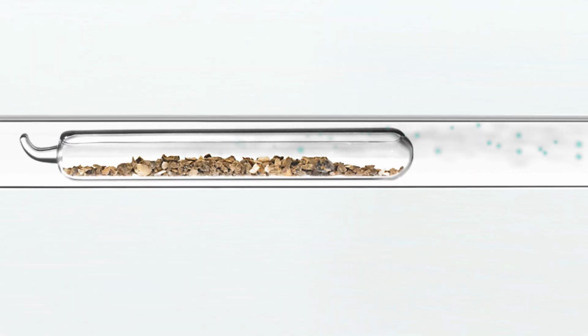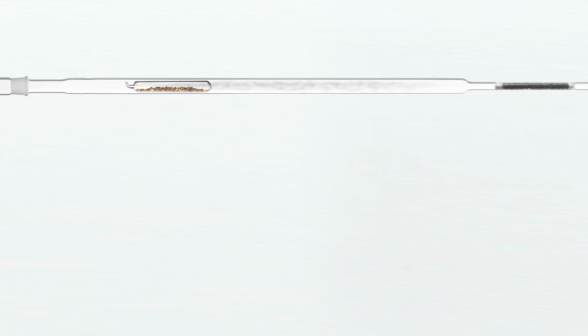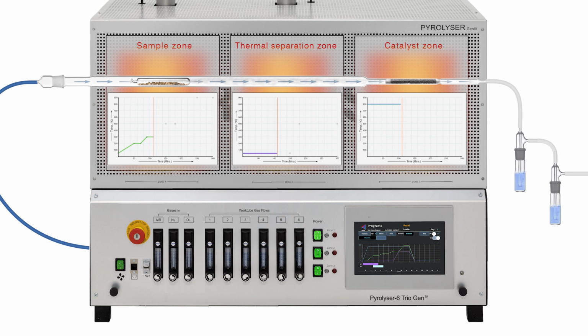Between 100 and 200 degrees C, water and some volatile species are liberated. By 200 degrees C, liberation of weakly bound tritium is mostly complete. Between 200 and 400 degrees C, more strongly bound tritium is liberated, and carbon compounds slowly volatilize and are carried through the catalyst bed to the external traps. In most cases, when the sample zone reaches 500 degrees C, the airflow is automatically changed to oxygen to ensure complete oxidation of the sample.